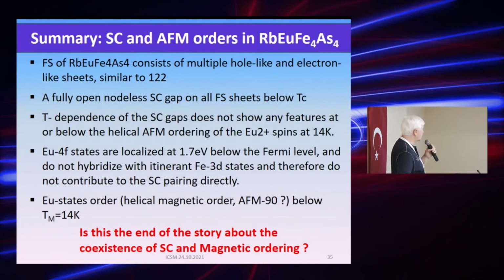Superconducting gaps don't show any features at the temperature of magnetic ordering of the europium spins. It would, however, be too premature to conclude that superconductivity and magnetism are fully decoupled. What we know for sure is that europium 4f states are located far away from the Fermi level, and therefore it is reasonable to expect that the itinerant electrons and localized moments do not interact strongly, at least in a simple way.